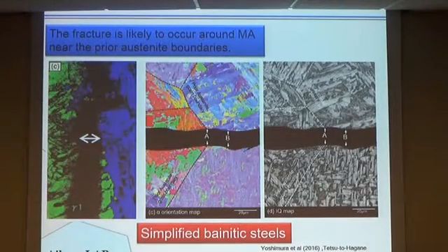In recent years, there are some researches about the trigger point of brittle fracture. According to these researches, the fracture is likely to occur around MA near the prior austenite boundaries. And this figure is the EBSD pattern of the trigger point of brittle fracture, and this line is the prior austenite boundaries, and here is the trigger point of the brittle fracture.